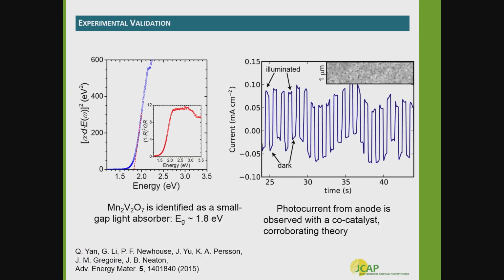And the theorists identified this manganese vanadate phase as a stable small band gap light absorber with a band gap of 1.8 eV, and very shortly thereafter the experimental team was able to identify and show that this band gap could be validated. And in high throughput experimentation, they were able to directly and immediately see photocurrent from photoanodes with a co-catalyst. And this whole effort took place in the course of a number of weeks rather than the usual materials development time cycle spanning from months to years.